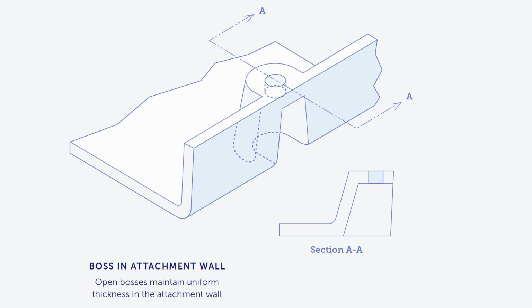To avoid shrinkage, the thickness and diameter of the boss are both very critical. We need to make sure that we design a smaller diameter for the screw hole to compensate for shrinkage. And the thickness of the boss should typically be no more than 60% of the total wall thickness.